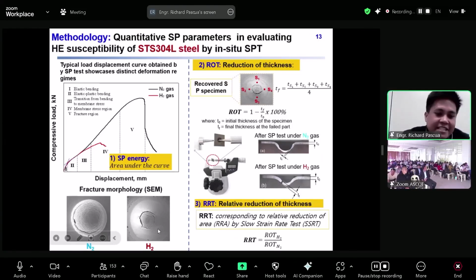Therefore, by utilizing this recovered specimen, we obtained our two remaining parameters, the reduction of thickness or ROT and the relative reduction of thickness or RRT, in which the reduction of thickness is derived from the final thickness and initial thickness of the sample. The final thickness was measured as the average thickness from the fracture region of the recovered specimen using a point micrometer. As you can see, this is the typical thickness that we obtained under nitrogen and hydrogen environments, in which a thinner thickness was observed under nitrogen compared to the hydrogen environment.